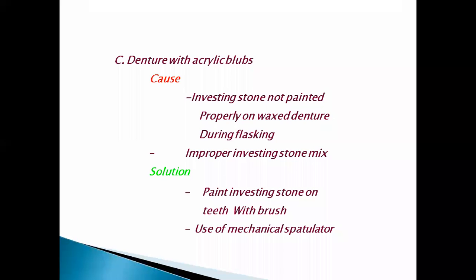Dentures can have blobs, a small spherical blob kind of thing over the denture surface. That generally occurs when you don't paint or pour the second pour very nicely, and the second pour does not wet the trial denture everywhere. So what will happen is when you dewax, there will be holes or voids in the plaster mold. And when you pack the acrylic in that, the acrylic will go into those voids and there will be small blobs on the surface of the acrylic denture.